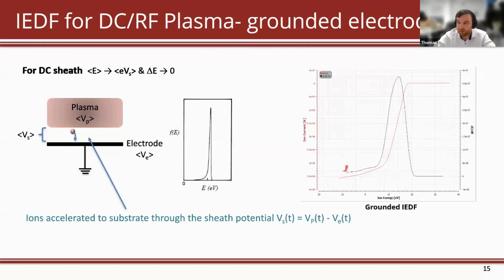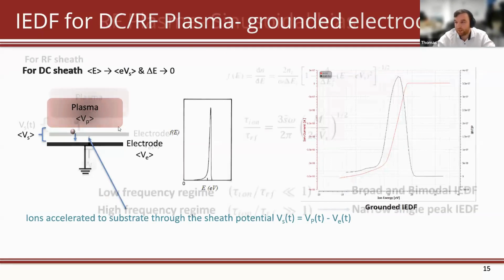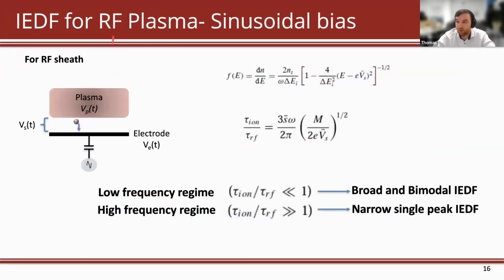I showed you this before, but this is what data would look like in a grounded situation where the peak is related to the plasma potential. And then if you have an RF driven plasma, the sheath is oscillating sinusoidally, so it gets more complicated. It also depends on the mass of the ion. If you have low frequencies, the ions can react quite strongly to the changing voltages, so you get these really broad bimodal IEDFs. I'll show you in a moment. And if you're using really high frequencies, you get narrow peaks. The problem with high frequencies is you don't get very much energy.